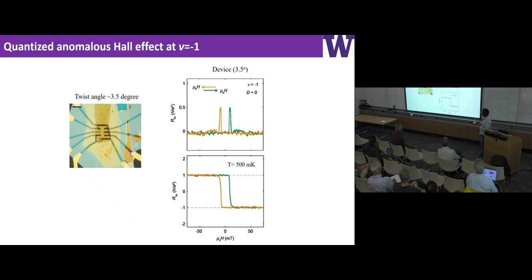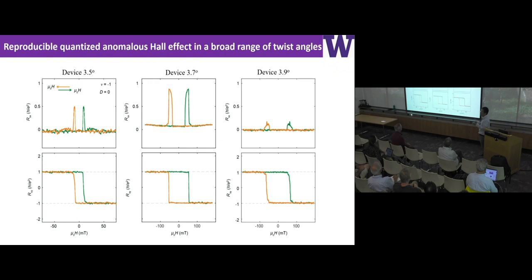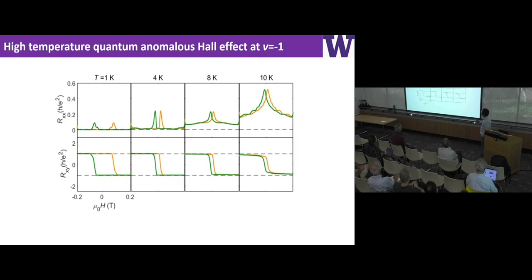Next, we do these magnetic field measurements, first at filling factor -1. You will see Rxy is quantized at h over e squared, with a nearly vanishing Rxx at zero magnetic field. This is precisely the hallmark of the quantum anomalous Hall effect. We measured it in three different devices with different twist angles, 3.5, 3.7, and 3.9, and they show very similar behaviors, so I think the results are really robust. The nice thing about this system is that you can apply an electric field to control the quantum anomalous Hall state.